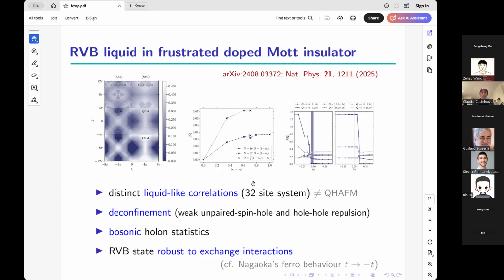to make strong claims. Another thing we did is to look at the hole-hole correlations when you have 2 holes in the system. And this is shown in the middle plot here as a function of hole-hole distance. The dashed bottom data are for the 32 sites system, and the top ones are for the 16 sites system. So we can actually just look at the 32 sites really. And what you can see, of course, they are hardcore, so 0 at 0, that doesn't tell us anything. The other data tell you that they are flattening out pretty quickly. They are perhaps slightly repulsive at lattice distance, but they are largely deconfined.